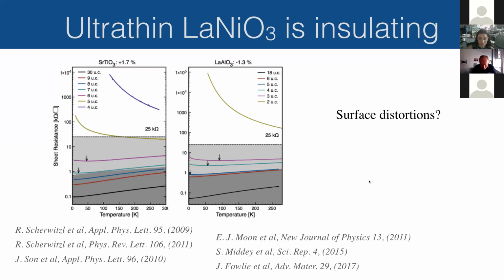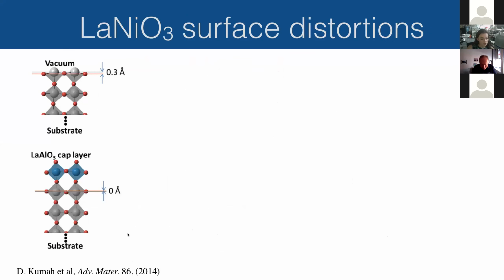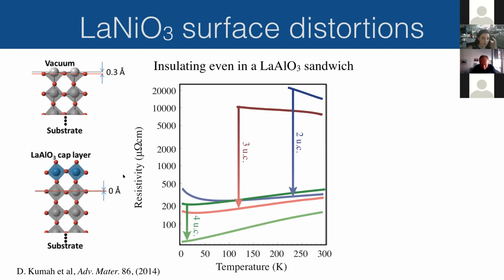Well, one reason could be surface distortions. This was a really beautiful study by the speaker of yesterday, actually, where they saw that on the surface of the lanthanum nickelate film, you have this buckling of the nickel-oxygen-nickel bond angle, and the nickel is lifted out of plane a bit and the oxygens are coming down a bit. So there's a huge distortion at the surface. They were managing to alleviate this distortion a little bit by putting a lanthanum aluminate cap on the top. So this kind of fixes the problem a little bit. But still, if you keep this lanthanum aluminate cap, it doesn't really matter because the sample is still going to be insulating if you make it thin enough.